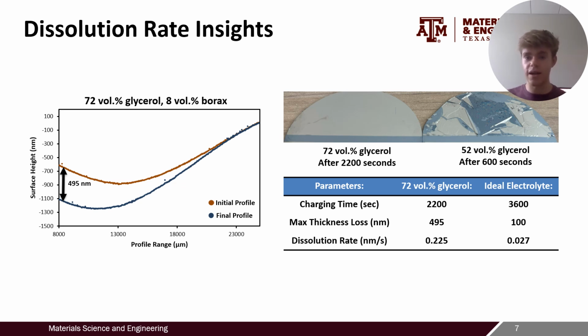I mean, 1 nanometer every 5 seconds isn't too bad, right? But since experimentation with NR would take around an hour, and this is using around a 100 nanometer film, both of these are kind of loose, but the ideal electrolyte would have a rate of negative 0.027 nanometers per second. So that's nearly 10 times smaller. And there's a lot of work to be done in reducing this general corrosion. But increasing the glycerol concentration in the electrolyte, at least for now, it appears to have the potential to work and to further decrease this to the point to where we can actually do the experiment.